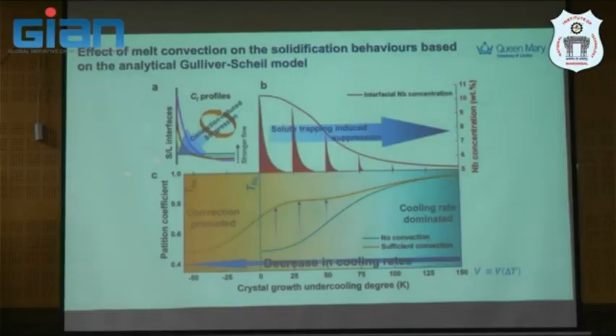This is a zone that you see, which we call the solute dilute zone, right? It's trapped in the melt pool, and we believe this is due to the effect of the melt convection during the printing. If you decrease the cooling rate here, let's say this is the solid liquid interface, and if you have the convection flow, it will actually increase this zone. So convection will suppress this, but a strong flow will go up here, and this solute trapping induced suppression will impact the niobium concentration. It will be from strong to suppress this zone.